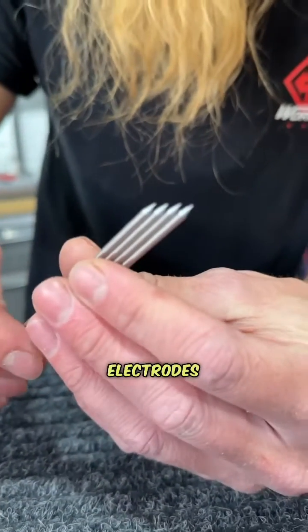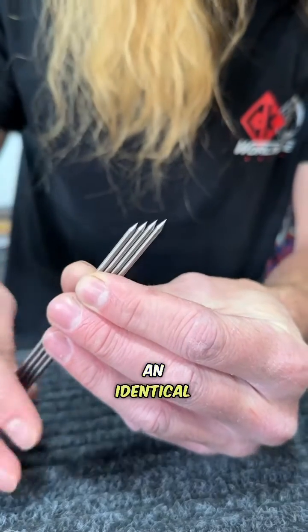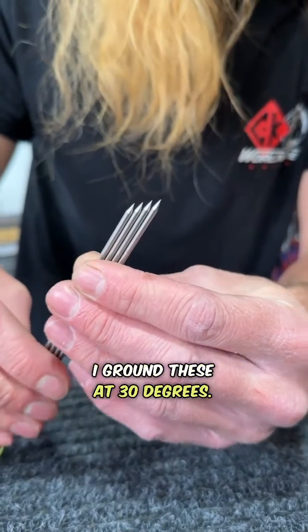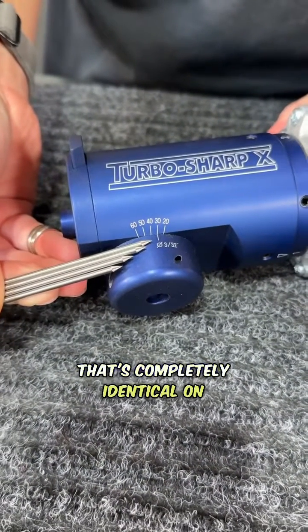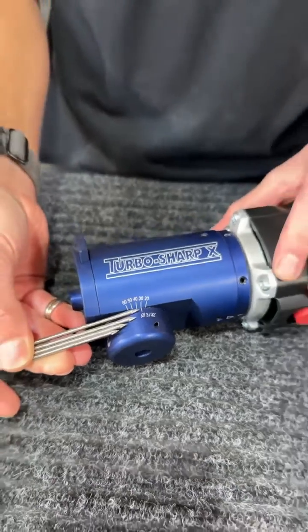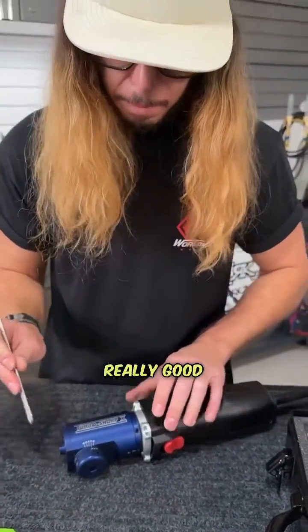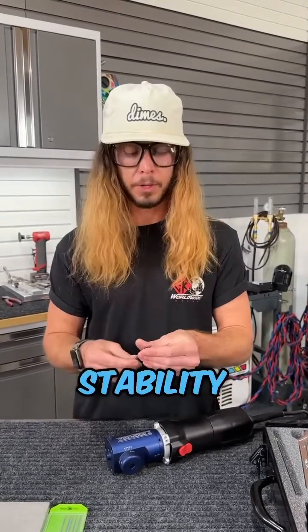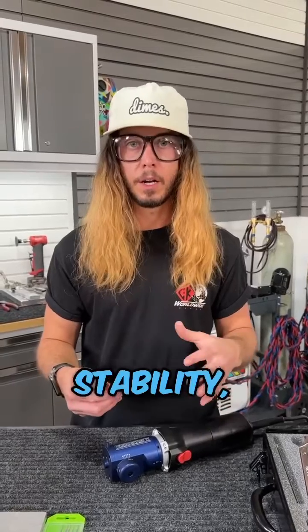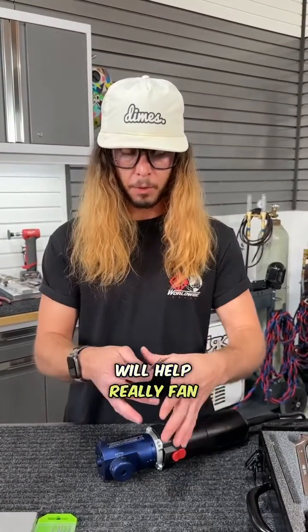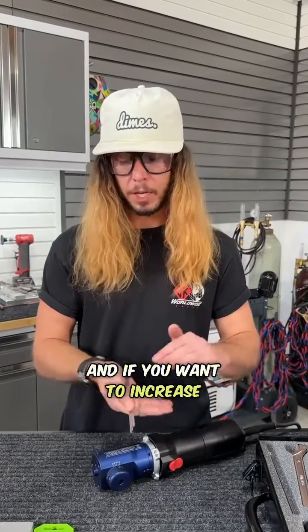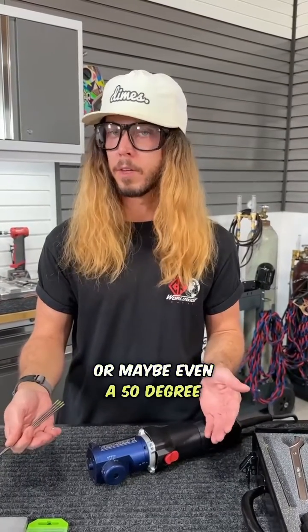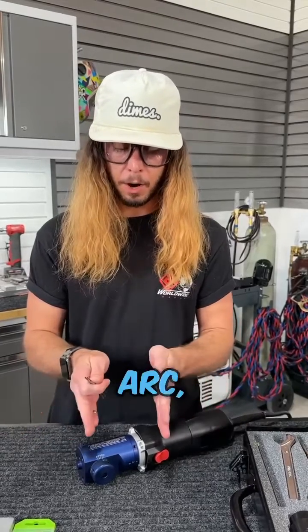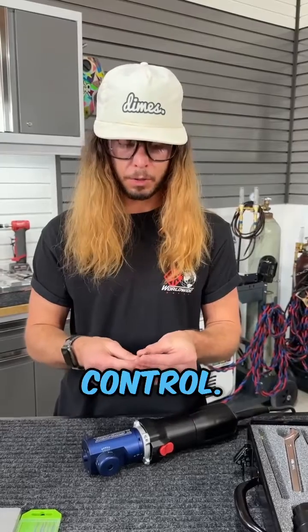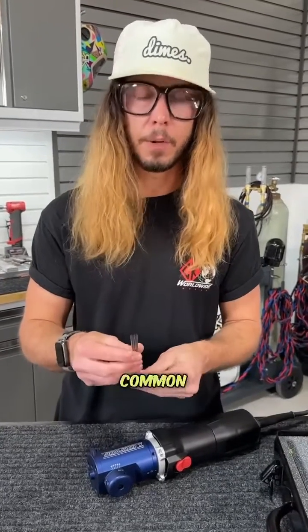So here I ground four of these electrodes and they have an identical grind angle on each electrode. I ground these at 30 degrees. So this is a 30 degree point that's completely identical on each of these electrode points. 30 degrees gives a really, really good medium ground, a good penetration profile, and really, really good arc stability and arc control. If you want to increase your arc control and stability, going to a 20 degree grind will help really fan that arc out and give you a really good control overall, but you're going to decrease the penetration depth. And if you want to increase that penetration depth, going towards like a 40 degree or maybe even a 50 degree tungsten grind angle is going to narrow that arc, increase your penetration depth, but it's going to be a little bit harder to control.